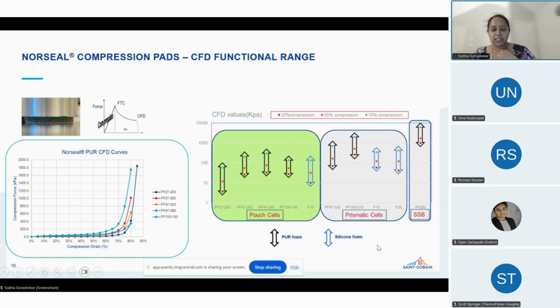And in some applications, there is also an additional requirement about flammability. So some of our customers want V0 rated products within the pack. So polyurethane foams have some restrictions when it comes to the flame rating. We cannot get a V0 rating unless we go to very high density, for example, 350 kg per cubic meter. That's the minimum density we need in a polyurethane foam to get to a V0 foam. Whereas silicone foams have this high flame rating, they also have high temperature resistance. So we offer both of these. But in terms of cost, the advantage is to use a polyurethane based solution because it's much cheaper and provides you a wide stress strain curve.